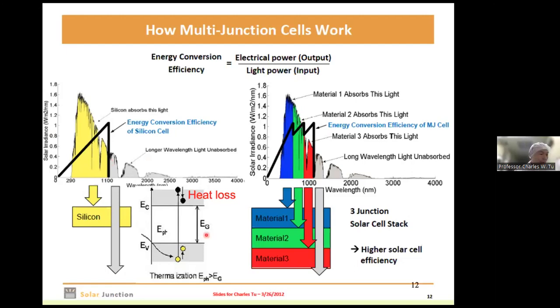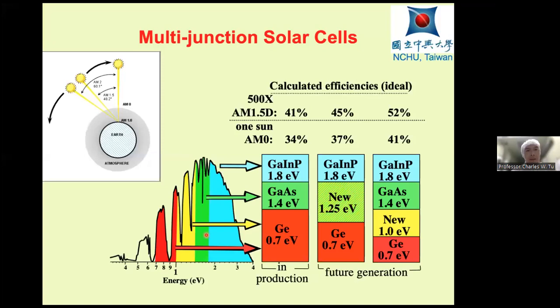Okay, and this shows the solar spectrum again, and the AM 1.5D is kind of the average solar spectrum. AM0 is without the atmosphere absorption. AM1 is on the Earth's surface, for perpendicular sunlight onto your solar cell, but because of the sun moving, we average to 1.5. So here we have 3 junctions. Or ideally we can have 4 junctions here, with germanium, which is lattice-matched to gallium arsenide,